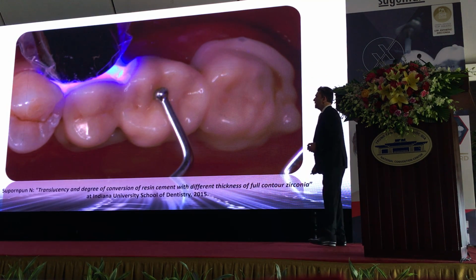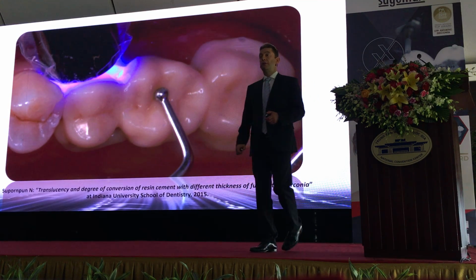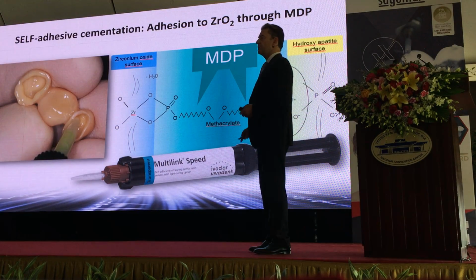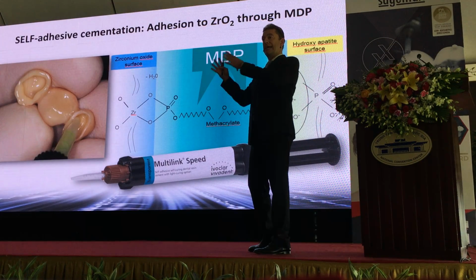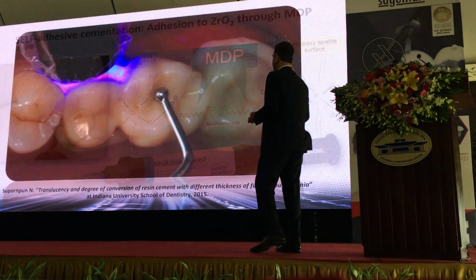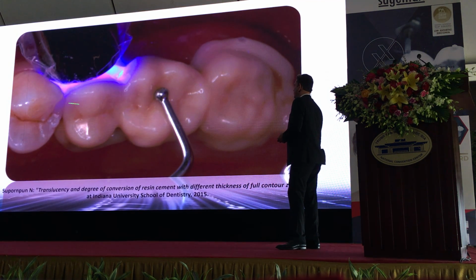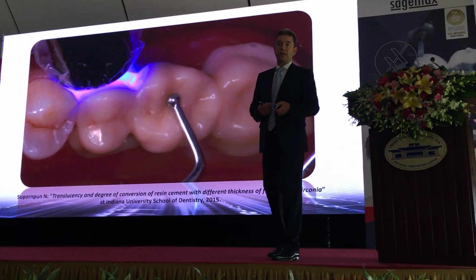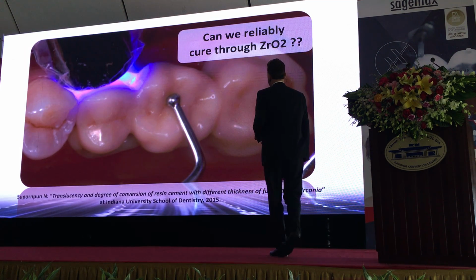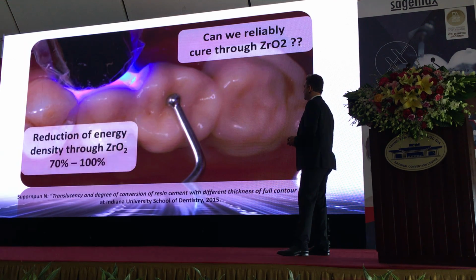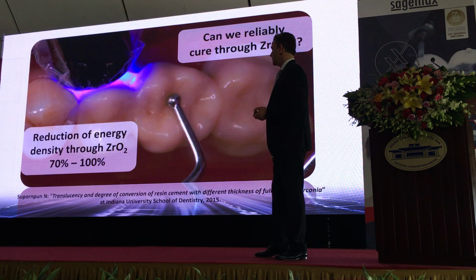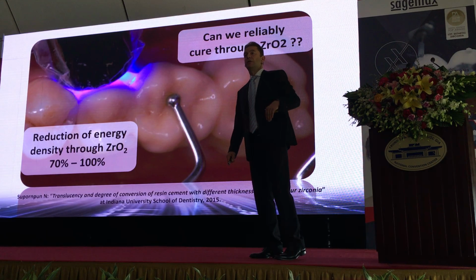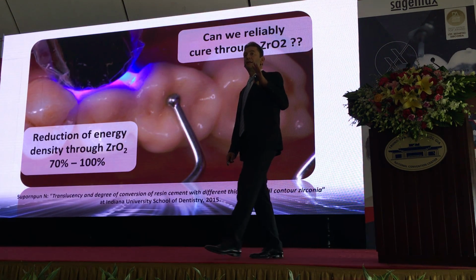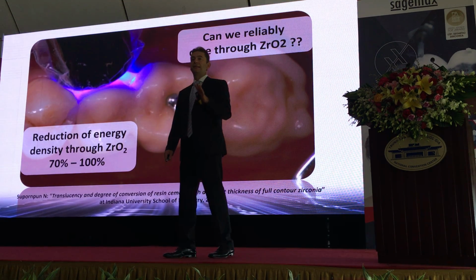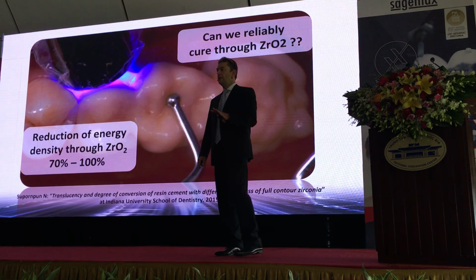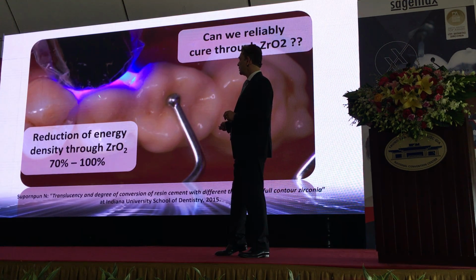Okay. Now, of course, very important is that we can cure the material. However, usually this material is dual curing. Dual curing means light curing and self-curing. With light curing, you can see there is not much light going through the zirconia because zirconia is not so translucent. So we are depending on a very good self-curing of the resin cement. The question is, how much light is going through the zirconia? Not much. You can see we have a reduction of between 70 and 100% of the light when we want to cure through zirconia. So if you are cementing zirconia, you must make sure that you select a cement that has a very strong self-cure, because you cannot rely on the light, as there's not much light going through.